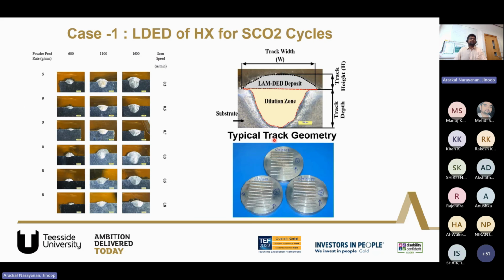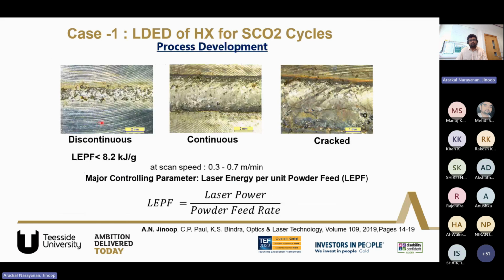heat exchanger. So it started off with single lines. As we normally start in additive manufacturing, we started with single lines at different process parameters, and then we developed the process window, the window of laser energy per unit powder feed, which is a combined process parameter that we use for developing the window.